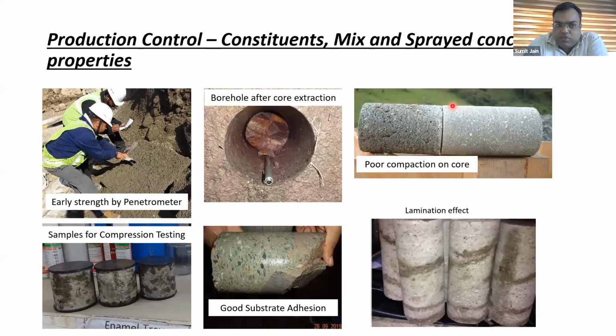These are some of the photographs for the production control. On the top left, you can see 2 engineers taking early strength by a penetrometer on a freshly sprayed shotcrete panel. The second image on top is the image of a borehole when you extract a core out of that borehole from the tunnel wall. And the central image at the bottom is the core which was extracted from this borehole.